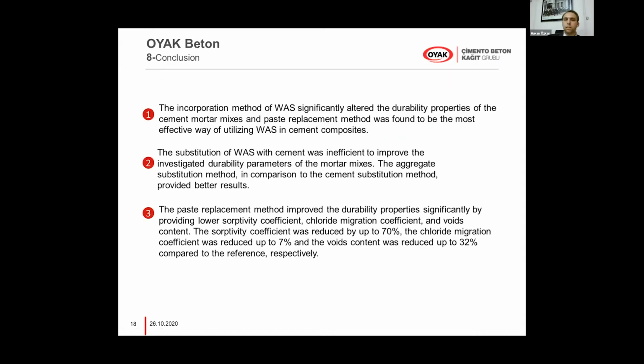As a conclusion, we can say that the paste replacement method was found to be the most effective way of utilizing WAS in cement composites. The aggregate substitution method provided better results in comparison to the cement substitution method. And for the paste replacement method, the sorptivity coefficient was reduced by up to 70%, the chloride migration coefficient was reduced by up to 7%, and the void content was reduced by up to 32% compared to the reference mortars. And we can also say that sorptivity and chloride migration coefficients have a good correlation with the void content. And that's all.